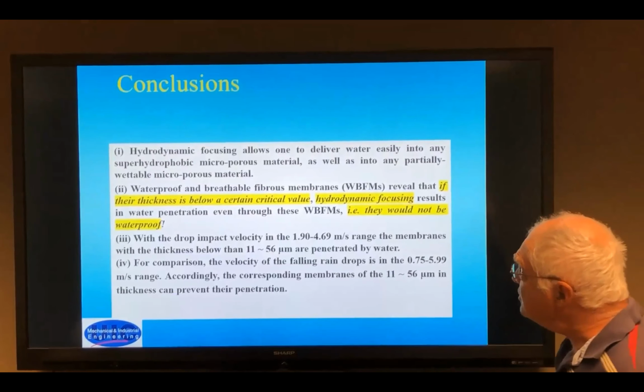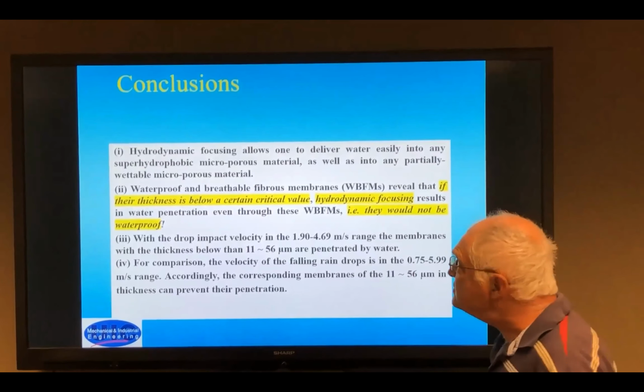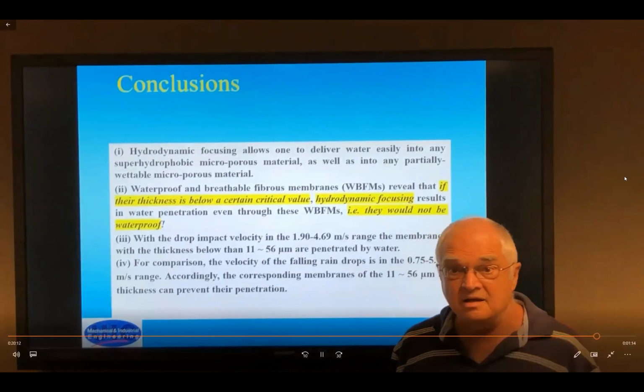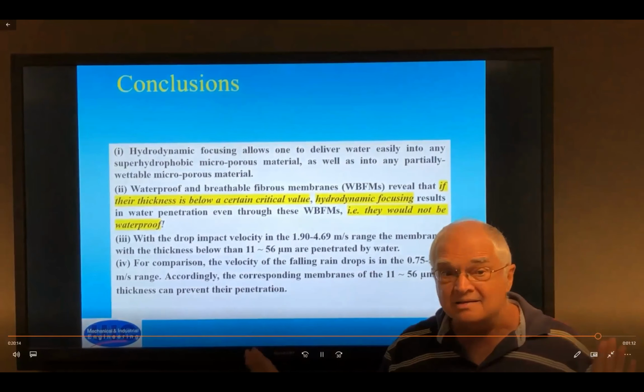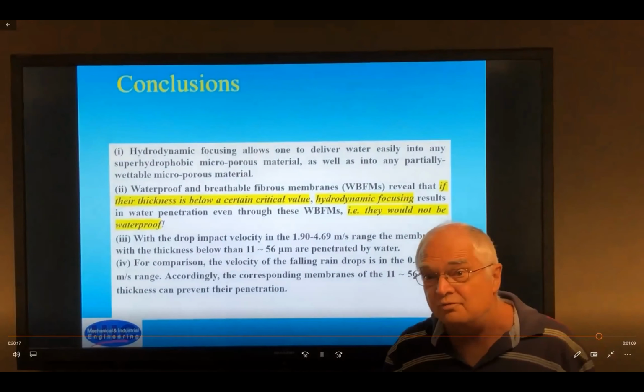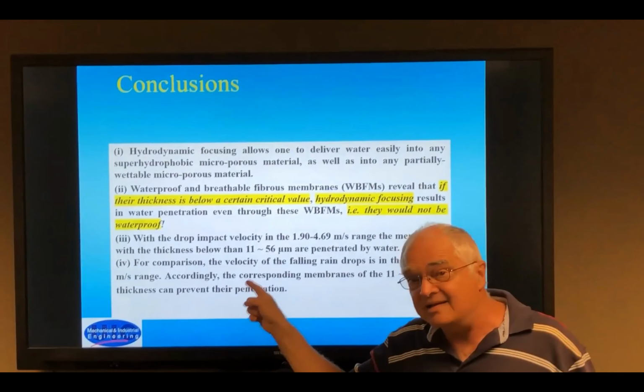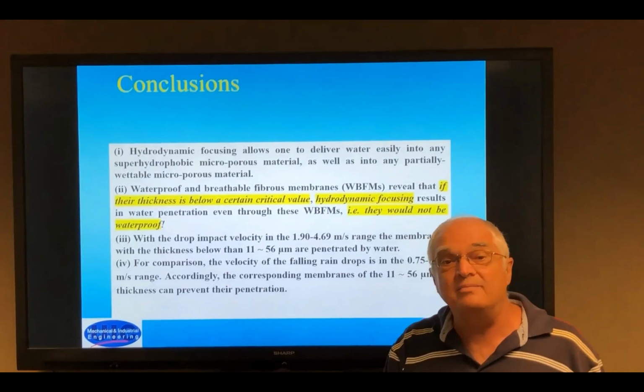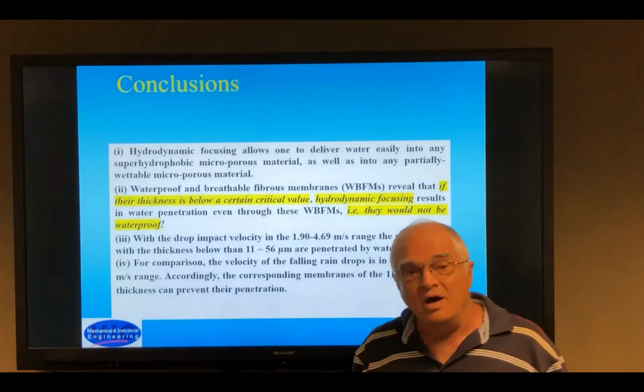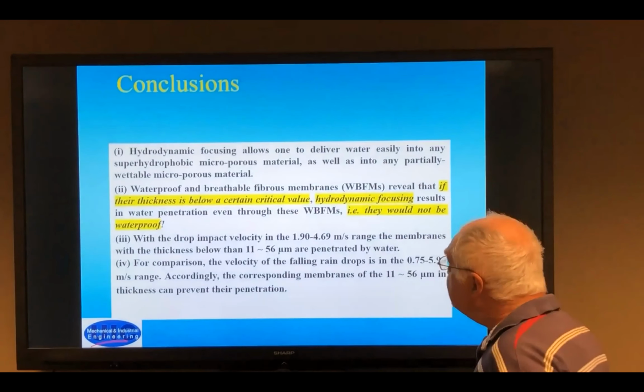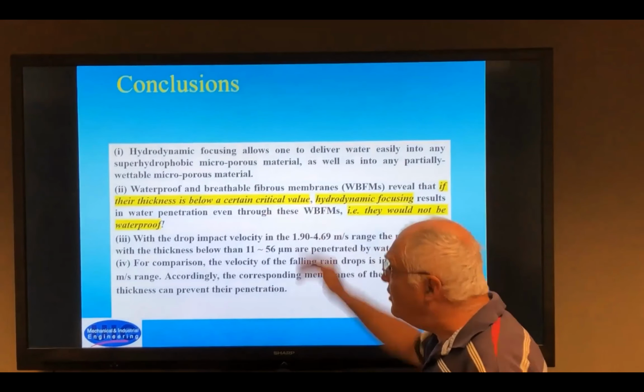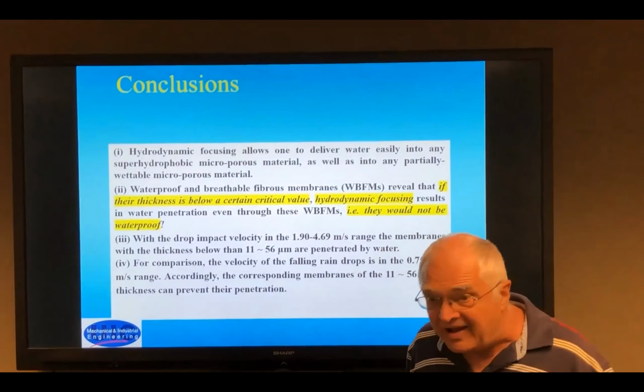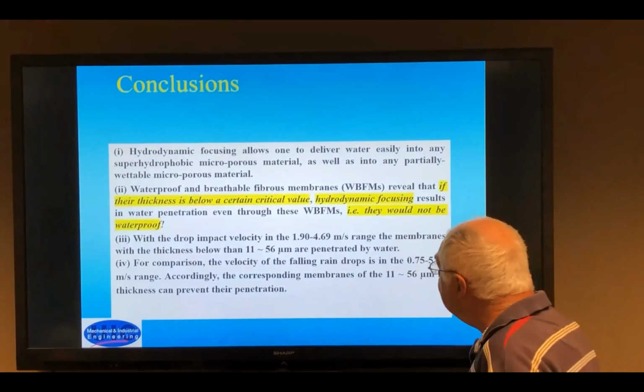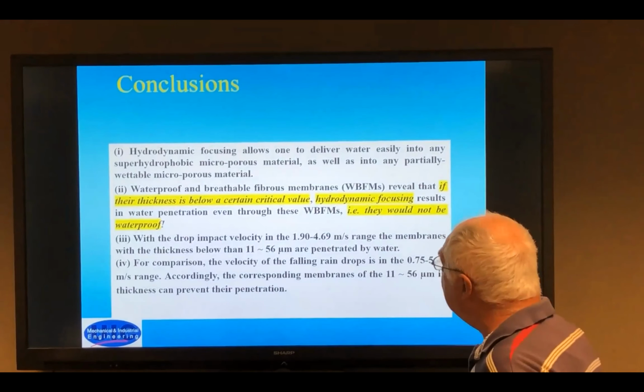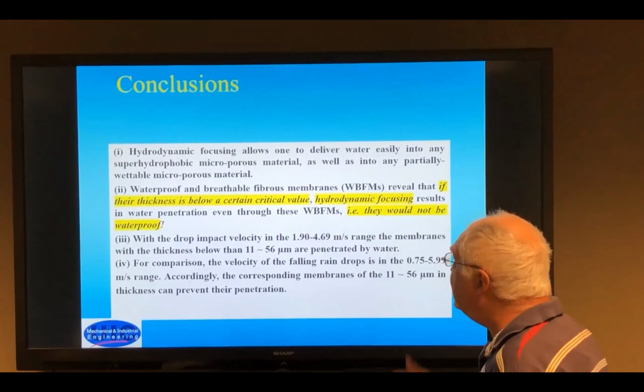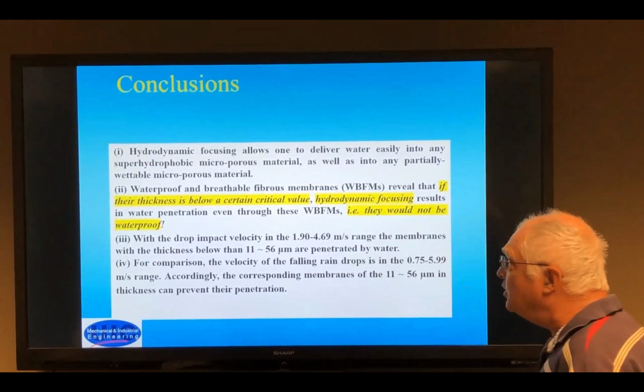So the conclusions are shown here. The hydrodynamic focusing essentially can bring water through any membrane, superhydrophobic, not superhydrophobic, and a dynamic test like that should be done to prove that the membrane can withstand water droplets. This is number one. Now, if you have a thickness below a critical value, the membrane fails. If you have a thickness higher than this critical value, then only then the membrane would be waterproof.